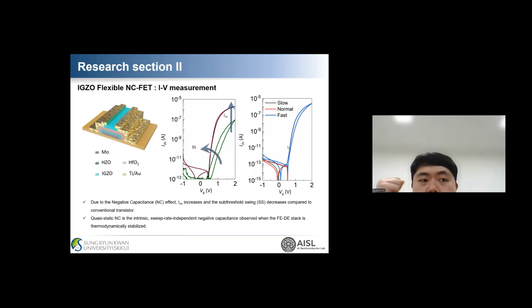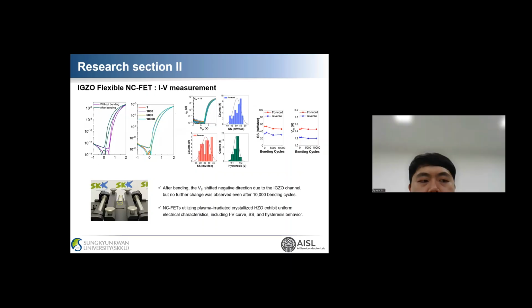In addition, even when the measurement speed was varied, no significant change in the characteristic was observed. This indicates that the behavior is not due to time-dependent switching effects, but rather reflects the quasi-static characteristic arising from a stable overall system. Since fabricating devices on a flexible substrate implies that they will undergo bending, we also performed the bending test on this transistor. Previous studies have reported that mechanical stress increases the donor concentration in amorphous oxides, which shifts the Fermi level closer to the conduction band and consequently shifts the turn-on voltage.